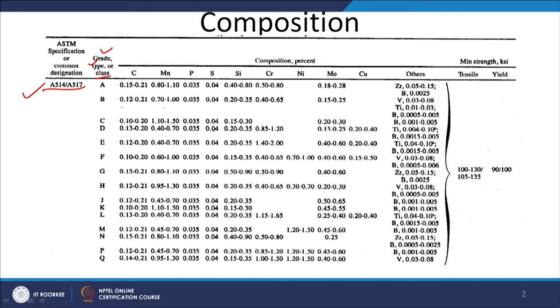For example, if we talk of the B grade steel having carbon 0.12 to 0.21, manganese 0.7 to 1, phosphorus and sulfur are very well below the acceptable maximum level, silicon 0.2 to 0.35, chromium is one typical element 0.4 to 0.65, and molybdenum is 0.15 to 0.25, and vanadium is 0.03 to 0.08, titanium 0.01 to 0.03, and boron 0.0005 to 0.005.